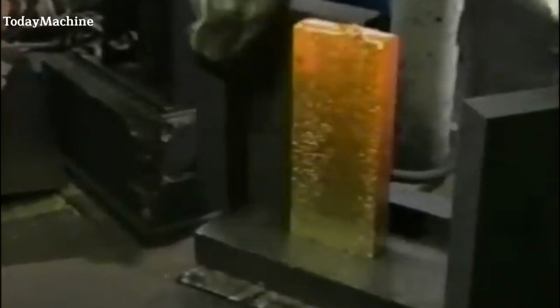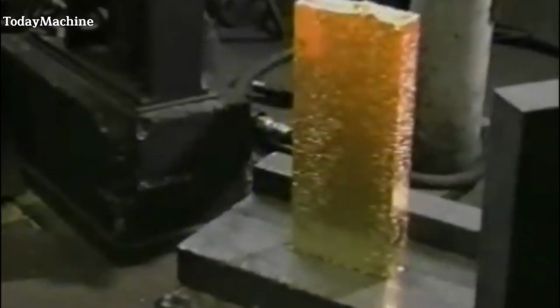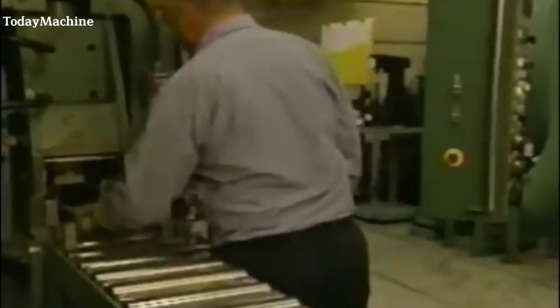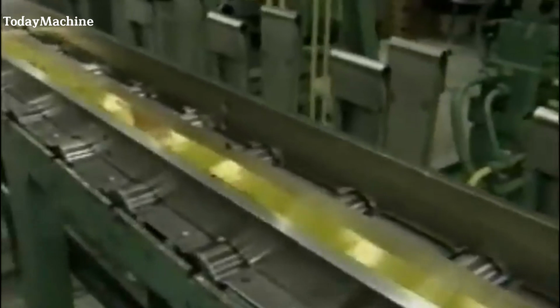Once refined, the gold is prepared for minting into coins and bullion bars. The purified gold is melted and poured into molds, forming ingots that weigh approximately 50 pounds. These ingots are then rolled to the desired thickness required for coin production. Due to the malleability of gold, the rolling process must be gradual to prevent cracking. Each ingot is passed through the rolling mill 12 times, reducing its thickness by nearly 10% with each pass. Initially 11.5 inches long, the gold is stretched into strips 12 feet long and less than 3 millimeters thick.